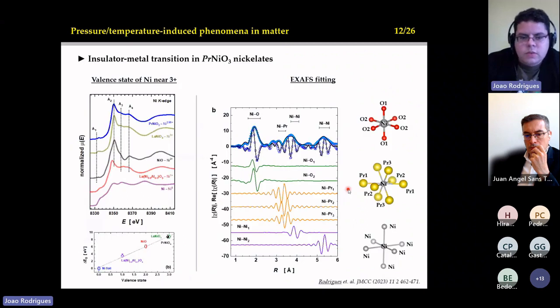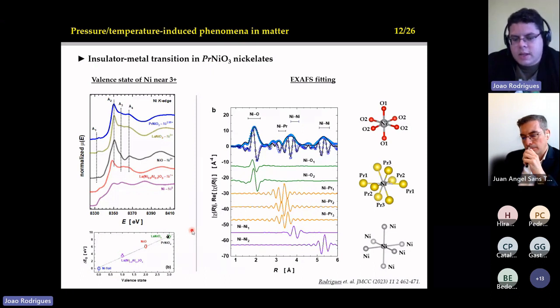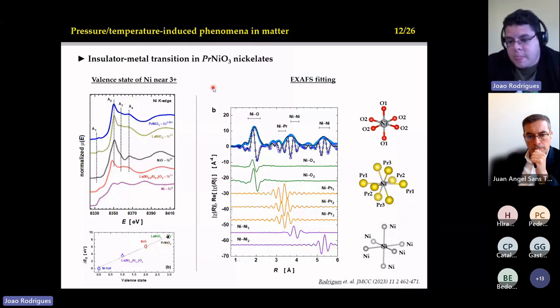Okay. So the first result that we have obtained was, okay, we need to check if my material has the nickel valence stabilized at this nickel site. And then we use different references, and then we can do a linear extrapolation. And we have managed to see that, okay, my praseodymium nickelate has nickel 3+. So my synthesis was very good. Just to mention that this sample was also synthesized under pressure, because nickel needs to change this valence. So this is a very unusual valence state, okay.